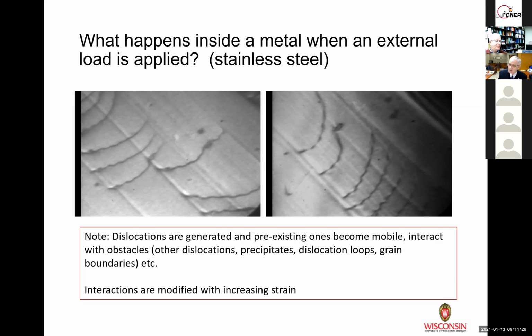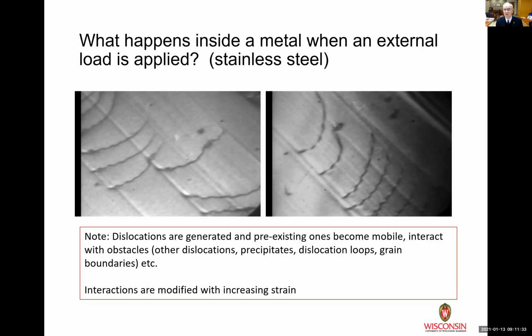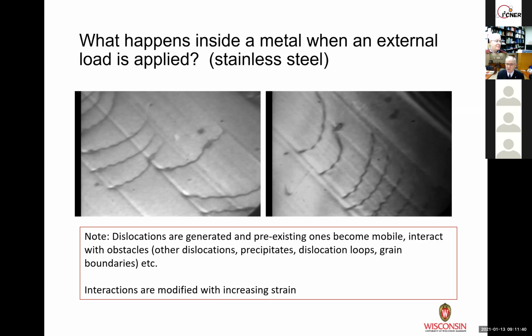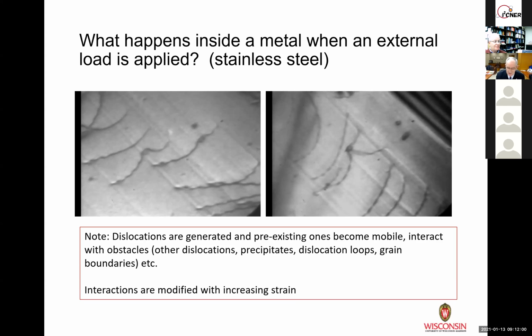So my first message I want to leave you with is, just because we might understand what happens when a material initially deforms, that interaction does not stay the same. Things change inside the material as the dislocations move and they interact with other precipitates. They're going to change when they interact with grain boundaries and with each other. So just because we understand dislocation mobility at the very early stages doesn't mean we understand it as a function of strain. So what happens is we keep applying more load to these.